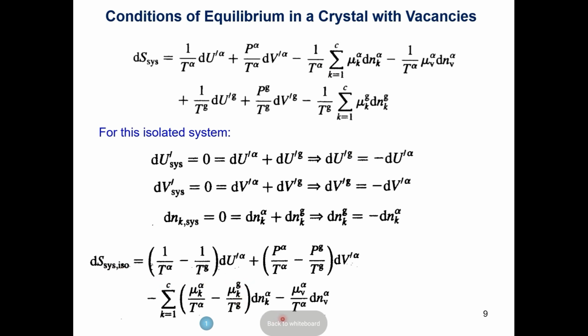You get an equation that looks something like this, which will illustrate that when your sample is in equilibrium, there are three conditions that need to be fulfilled. Thermal equilibrium means the temperature of the solid has to equal the temperature of the gas phase. Mechanical equilibrium comes from the fact that pressure in the solid equals pressure in the gas. The third criterion, chemical equilibrium, means the chemical potential of a given component in the solid has to equal the chemical potential of the same component in the gas—for example, chemical potential of oxygen in your TiO2 has to equal chemical potential of oxygen in the gas. Otherwise your sample has not attained equilibrium.